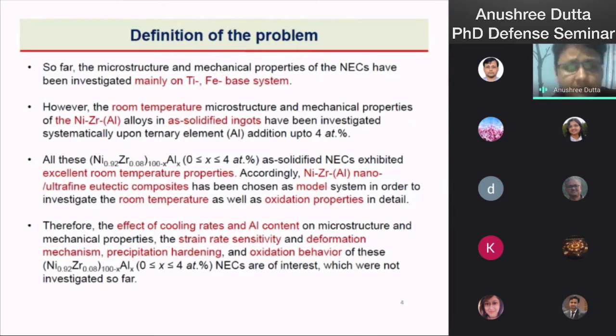Definition of my problem. So far, the microstructure and mechanical properties of nano-eutectic composites have been developed mainly in titanium-iron-based systems. However, the room temperature microstructure and mechanical properties have been investigated in nickel-zirconium-aluminum alloys up to 4 atom percent aluminum content. These alloys exhibited superior room temperature properties, and therefore nickel-zirconium-aluminum composites have been chosen as a model system to investigate room temperature as well as oxidation properties in detail. Therefore, the effect of cooling rate and aluminum content on microstructure, mechanical properties, strain rate sensitivity, deformation mechanism, precipitation hardening and oxidation behavior of Ni0.92Zr0.08 (100-x) Alx, up to 4 atom percent NECs, is of interest, which has not been investigated so far.